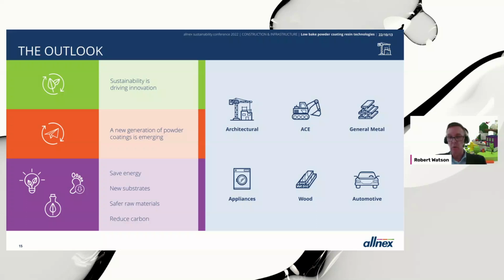And what I'd like to say at this point is, I mentioned earlier that there's been no new cross-linker chemistry brought to the market in 30 years. Within allnex, we're changing that. Where our research efforts into ultra-low bake cure are looking at alternative curing chemistries that allow us to break through that, I won't call it a glass ceiling, it's more of a glass floor of low temperature cure. And we're very excited about that. And there's a lot of effort and energy being put into that by the technicians here at allnex.